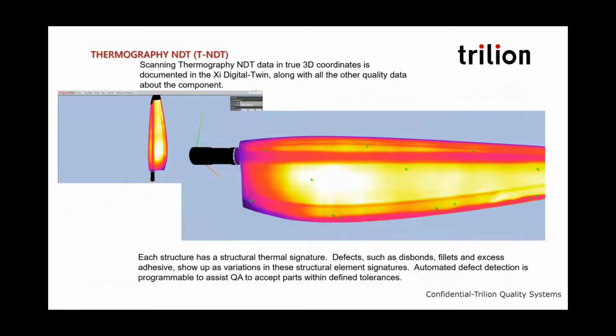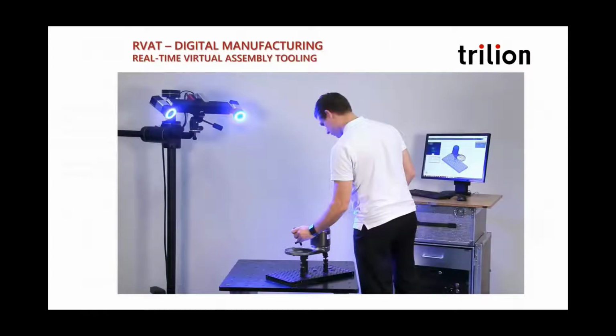Typical example of the same thing. In this case, we use a thermal sensor, and we just ran the thermal sensor with a heat source across the material. Here you're seeing the bond line thicknesses, the internal structure, typically with thin-skin materials. And this works nicely. We're coupled with an ultrasound producer, where the ultrasound robot can scan a part and look at the internal structure, and the thermography can look at the surface and understand the surface results that the ultrasound can't really see.